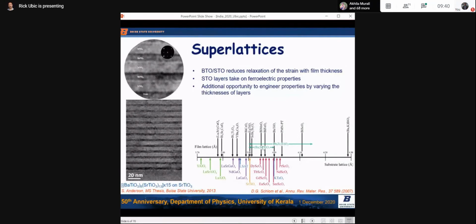And this diagram, I just like this diagram. It was published, gosh, over 10 years ago now. But it shows different substrate materials, perovskites, and the different perovskites you might want to put on them as films. And if you want to lattice match, this is a sort of graphical way of showing how to lattice match. If you want a lattice match for this, you use something that's near here in the substrates. But if you want to be very precise, you need something more than just this gross sort of graphical representation. So that's where this work is more or less coming from. And that's about the year we started, actually. In 2007 was the date of our first paper in this field.